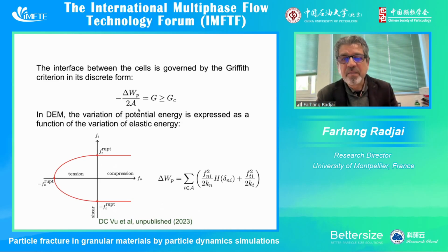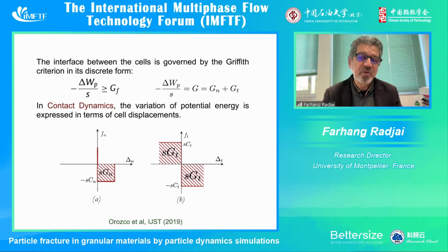And when the energy release rate is above this critical value of the energy release rate, the interface breaks. And that gives rise to a local form of the yield surface, as you can see here. So it can also be used as a yield surface, but it's better to use it point by point when we have an interface between two polyhedra rather than using a yield surface. But a yield surface works also. So it's based on energy, but also we can have a threshold. So this method can be used both as a yield surface and as an energy-based criterion, which is shown here. I will not go into the details. This work was done during the thesis of Luisa Orozco in Montpellier in 2019.